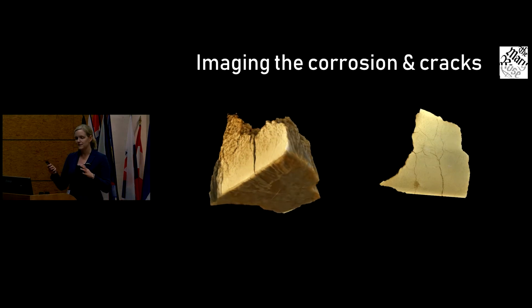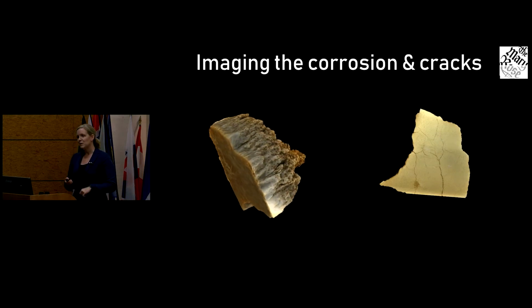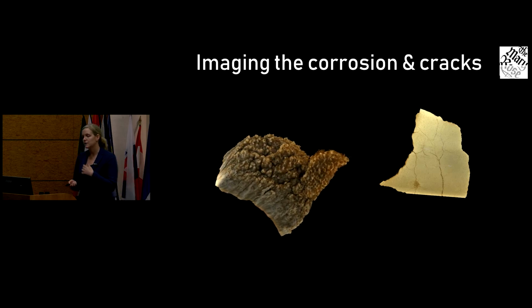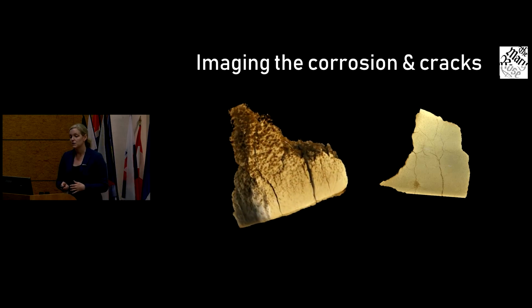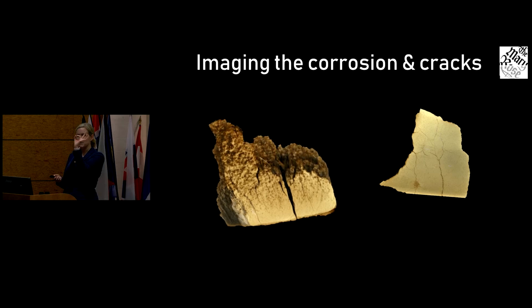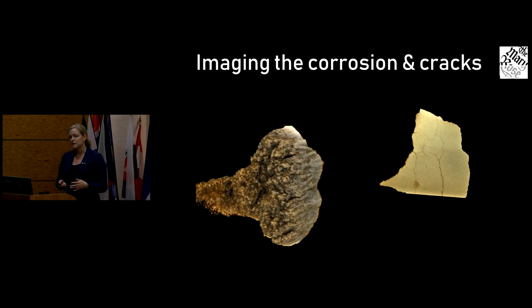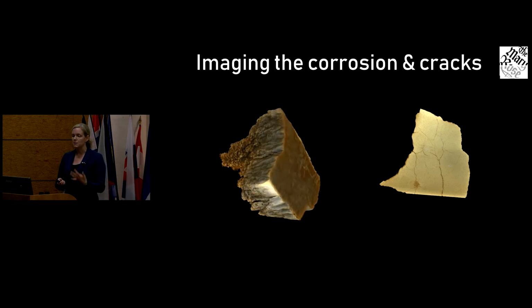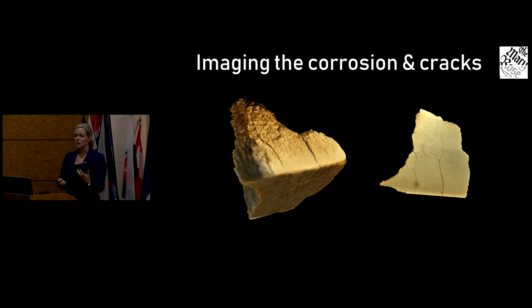We've also done tomography. This was at I-12 at Diamond. So first of all, just visually looking at this, this is a segment about this big. So the darker phases are the corrosion. You can see where the cracks are. You can see where the surface is. So this is obviously just showing you it as a whole.